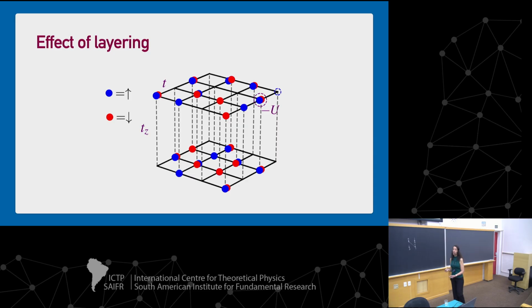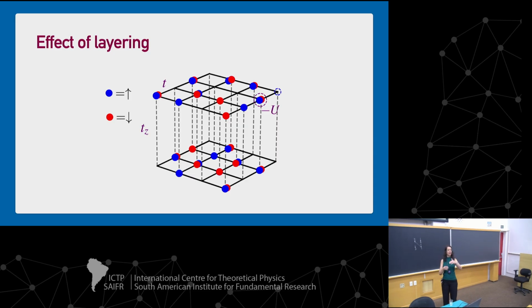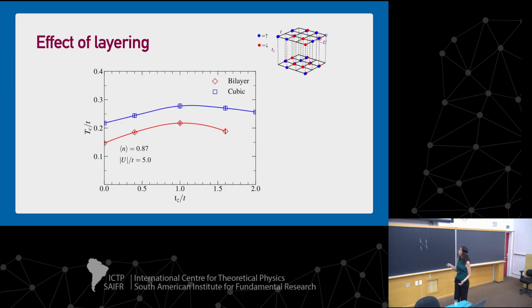One thing we also thought, as the experiments now can be done in layers, is if we add 2 layers, is it going to help increase the critical temperature or not? And so Rodrigo also looked at that. This is what happens when you have a bilayer in red and when you have a cubic lattice in blue. And this is the hopping along the perpendicular direction. So you have 2 layers and you have a hopping t within the layer, but the hopping between different layers can be tuned to different values. And we see that if we do this, there is an increase in the critical temperature, kind of above 0.2, so maybe it's useful for experiments.